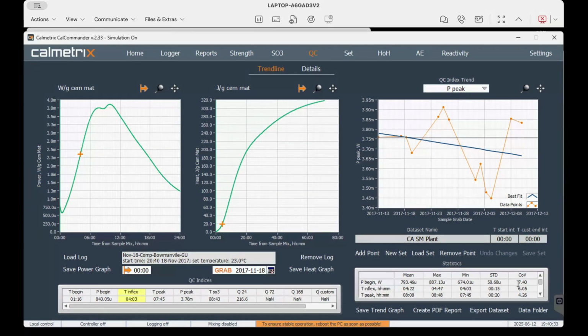For those who are not familiar with it, because not everybody maybe knows, coefficient of variation is the standard deviation divided by the average. And it's expressed in a percent. And a percent like 7.4 is not good, but it's not horrible. For something that's really tightly quality controlled in general, not just in cement, you would be less than 1%. But honestly, in cement, I have not seen a tight control like this on some of those parameters. Being less than 1% is almost impossible. It's almost easier to do in concrete.